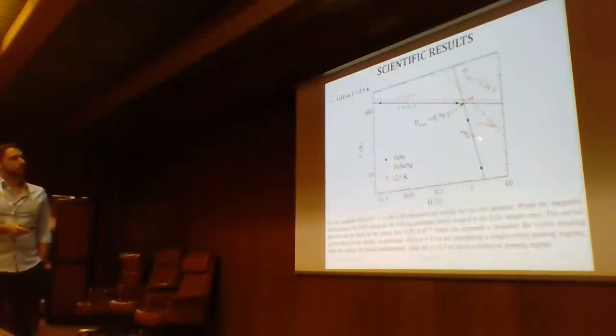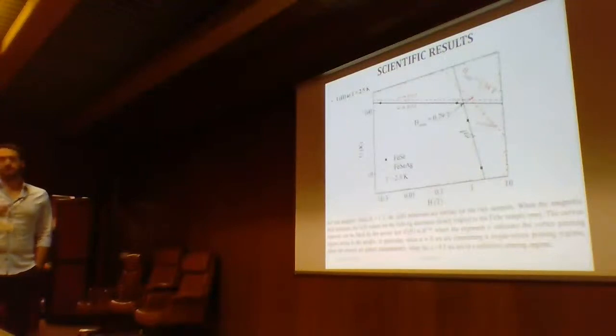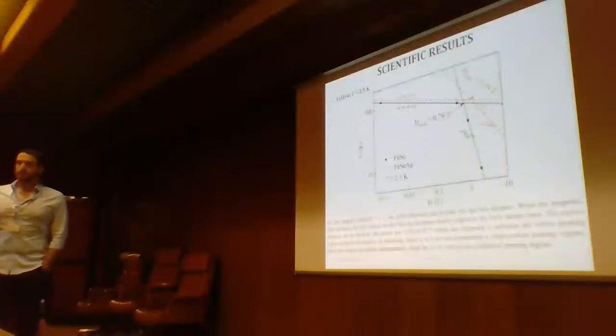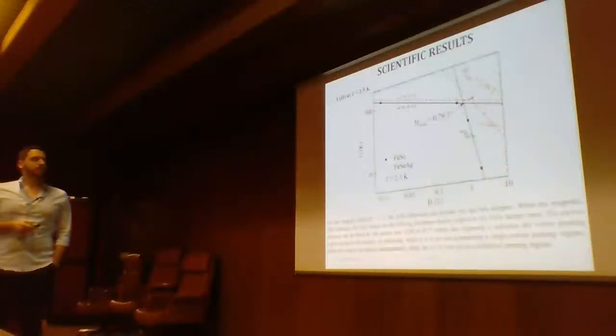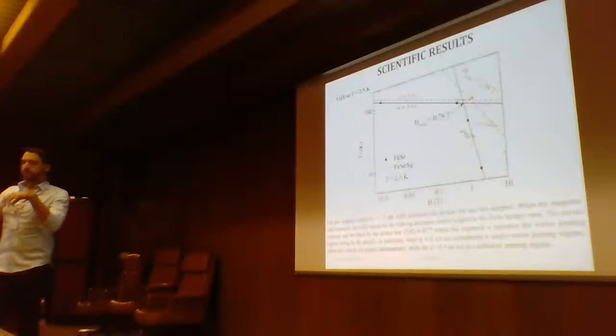While here the alpha values are 0.65 and 2.2. So when your alpha values are above 0.5, and this is the case, you are considering a collective pinning regime, which is a weaker pinning regime, in which the vortices are interacting with each other.